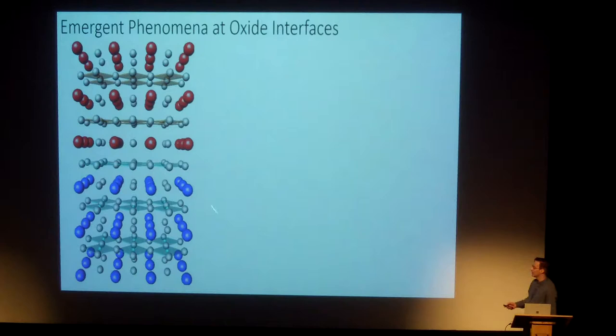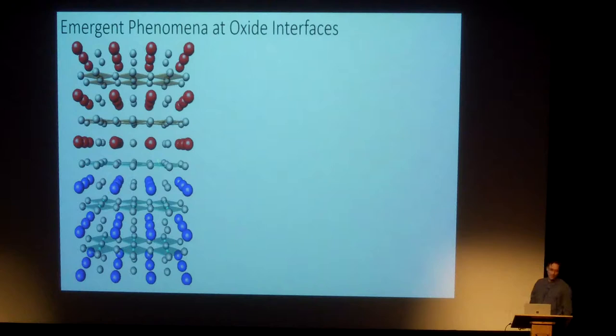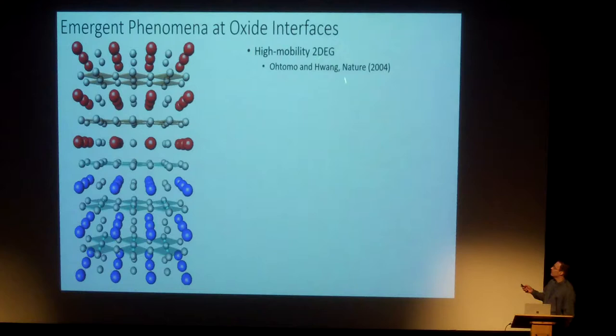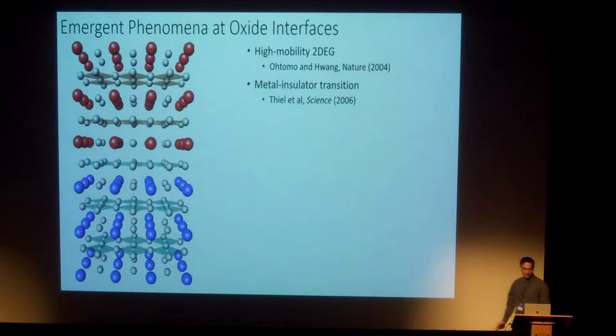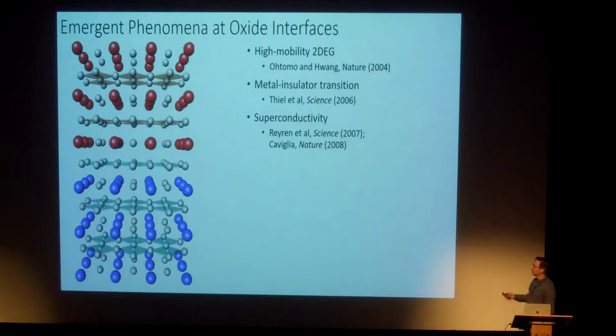My emphasis centers on what happens when you put strontium titanate in proximity with a thin layer of another perovskite, lanthanum aluminate. The physics is dominated by the strontium titanate but influenced by the boundary condition of the lanthanum aluminate. It was discovered by Harold Hwang at Bell Laboratories that when you take these two insulators and put them together, you can get a high-mobility conductor at low temperatures. Properties like superconductivity, magnetism, and tunable spin-orbit interactions are then revealed in two-dimensional form.